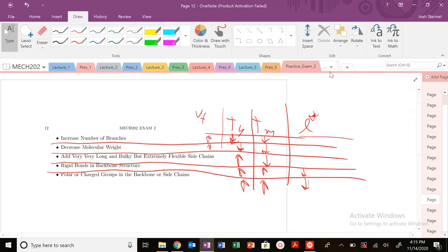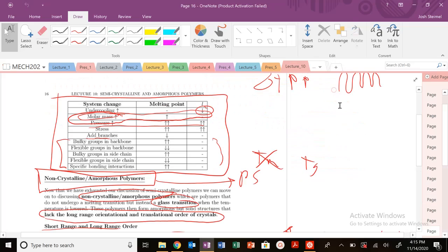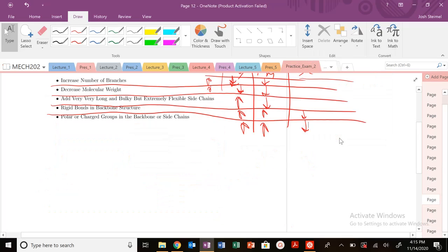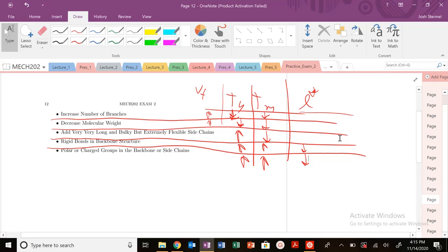So you can see the difference in this. Let's go back to our chain here. The critical lamellar thickness is still going to depend on your kinetic parameters, but you can estimate that critical lamellar size. So what about very long, bulky, but again, flexible side chains? That's going to be a little bit of a fuzzy issue. It's going to be fairly difficult, it's going to increase. Again, very flexible, I'm going to have to increase that lamellar thickness in order to overcome that gain in entropic